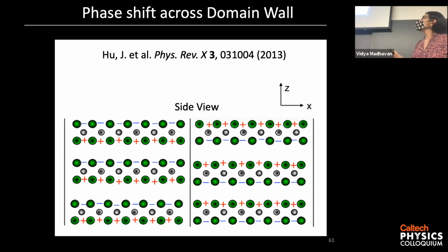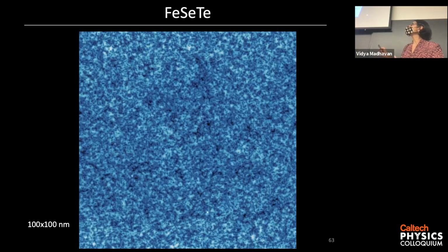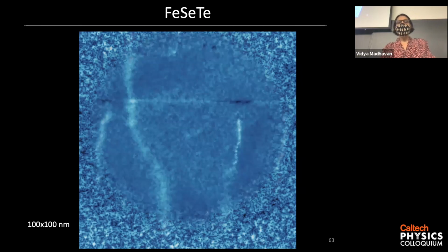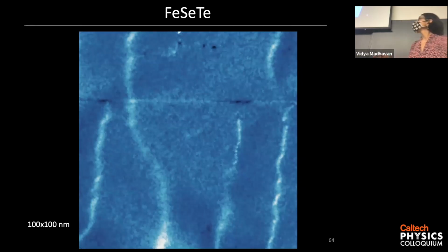So like I told you, this material, you can actually have regions where the crystal is flipped. So imagine you have a region where on one side, you have this kind of stacking, and the other side, you have a different stacking, basically a flip stacking. It's called a stacking fault. Then right at this boundary, you have the situation where perhaps superconductivity shows a phase shift. So we went searching for such domain walls. So a lot of our sample looks like this, very nice, no domain walls. But then once in a while, you can find regions where domain walls snake across the sample.